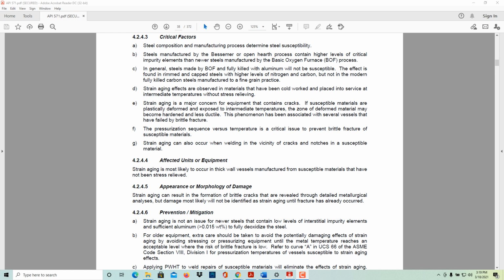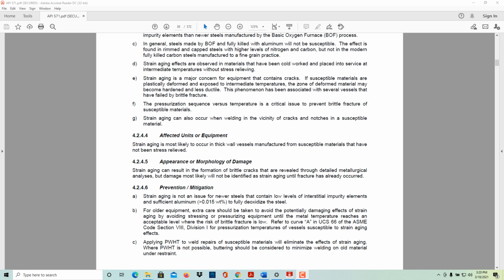The pressurization sequence versus temperature is a critical issue to brittle fracture of susceptible materials. Strain aging can also occur when welding in the vicinity of cracks and notches in a susceptible material. Strain aging is most likely to occur in thick wall vessels manufactured from susceptible materials that have not been stress relieved.